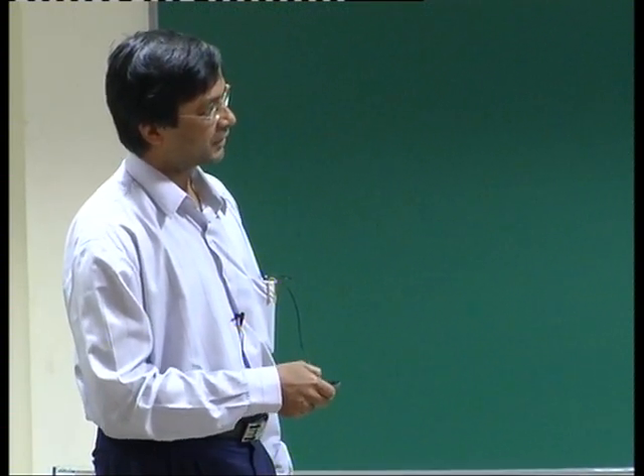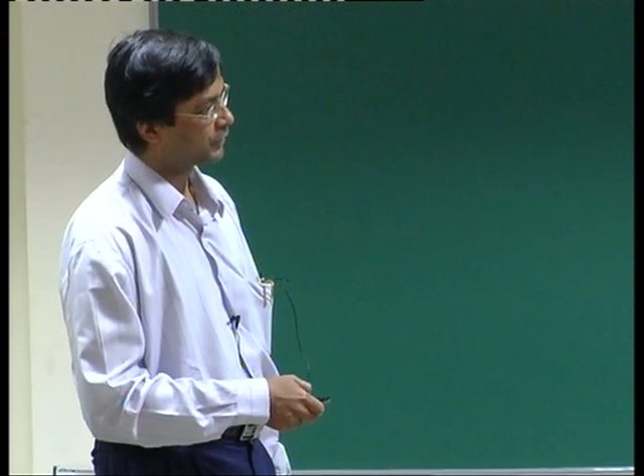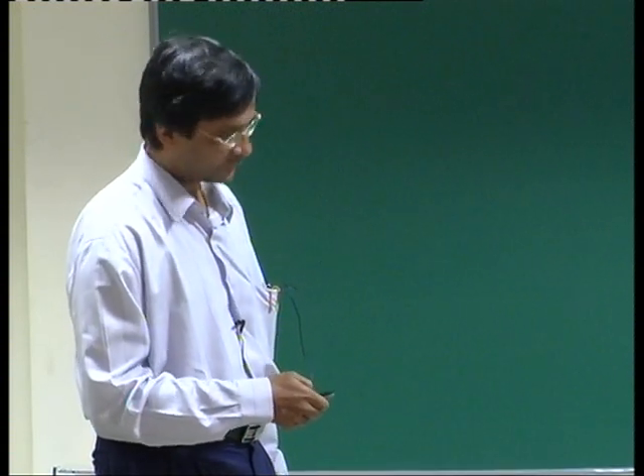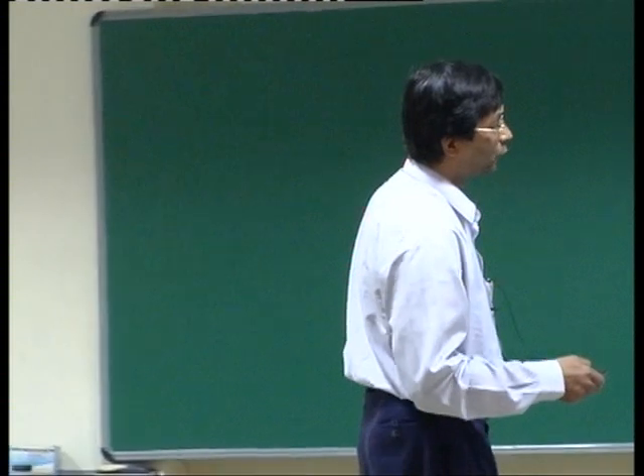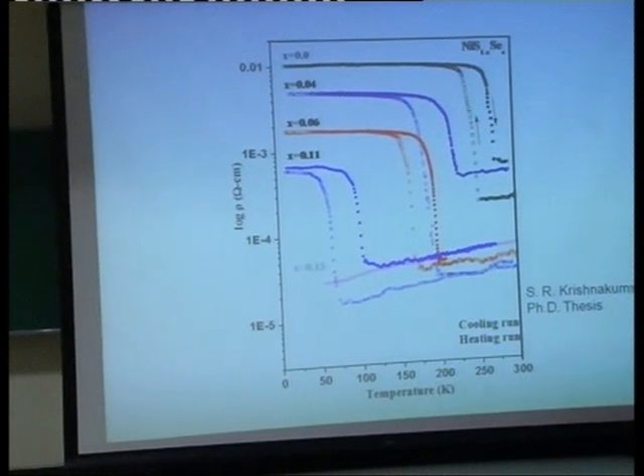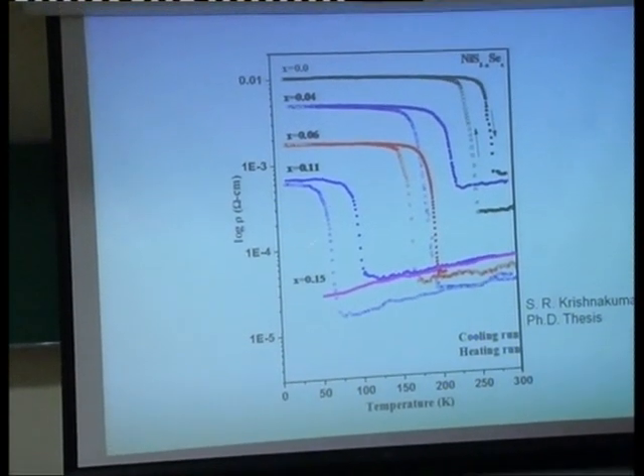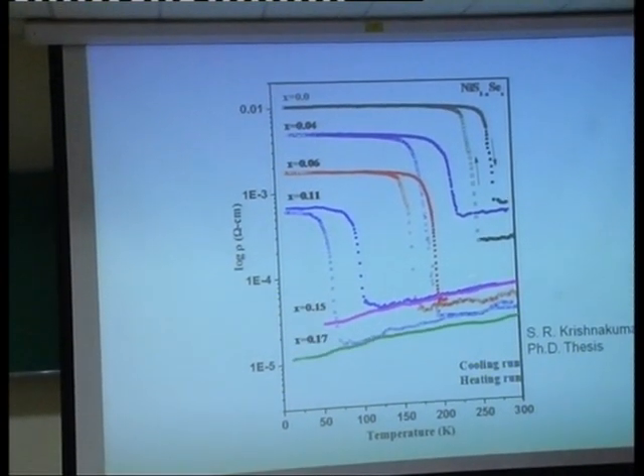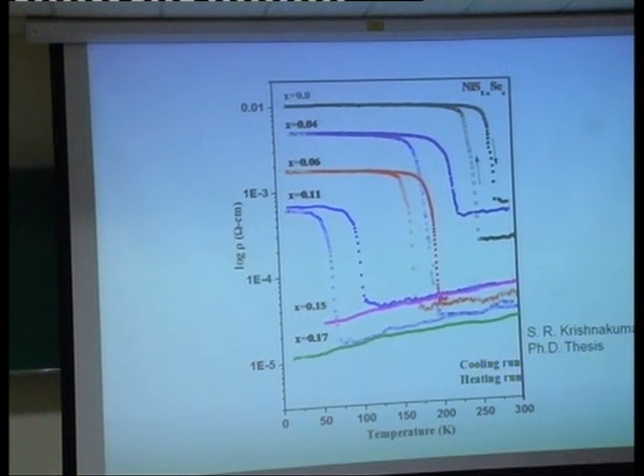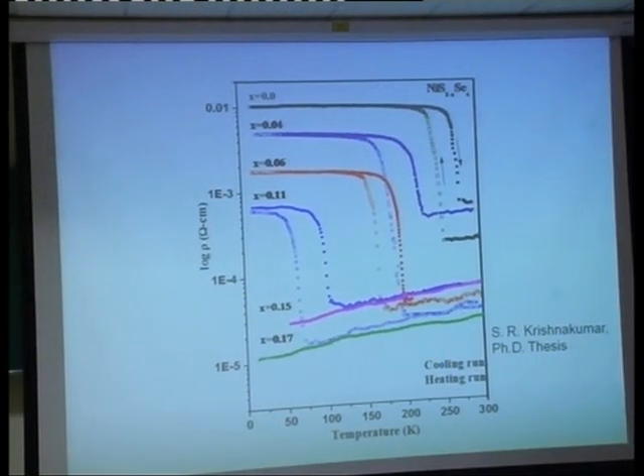And let me first illustrate how we can affect this phase transition by changing the selenium content, and that's shown over here. If I put 4% selenium, or 6%, or 11%, I keep pushing the transition temperature down. If I go beyond 14% or so, 15% and 17% ends up being a very good paramagnetic metal.